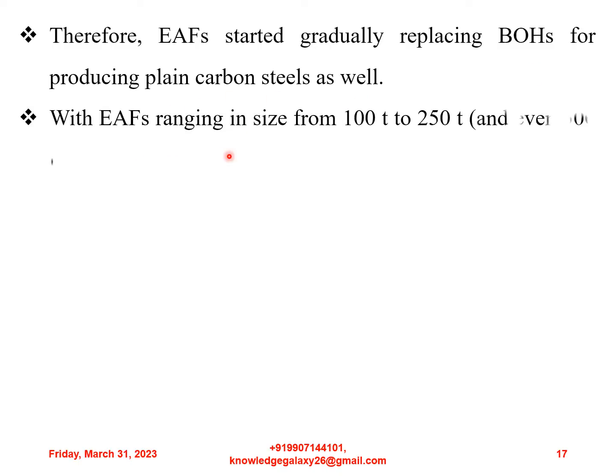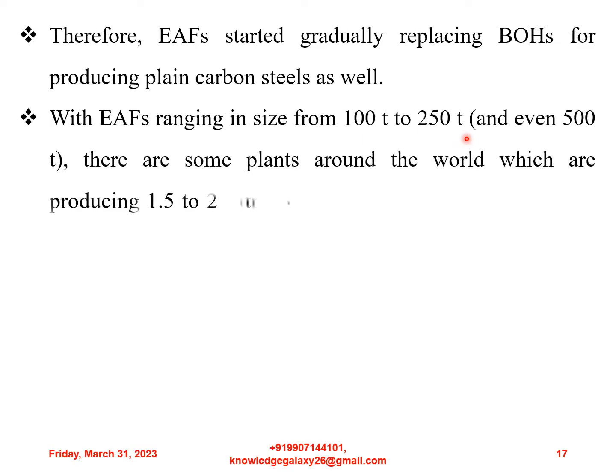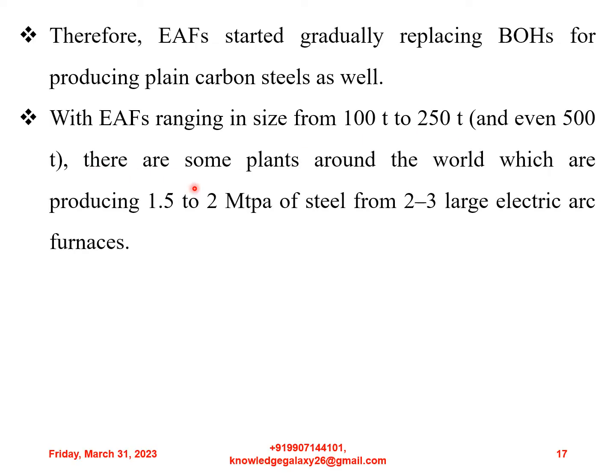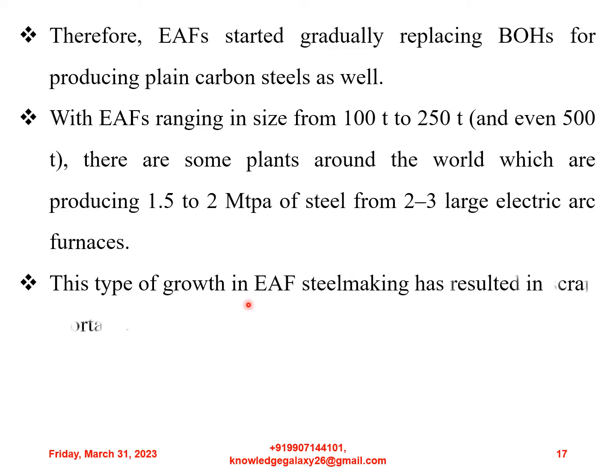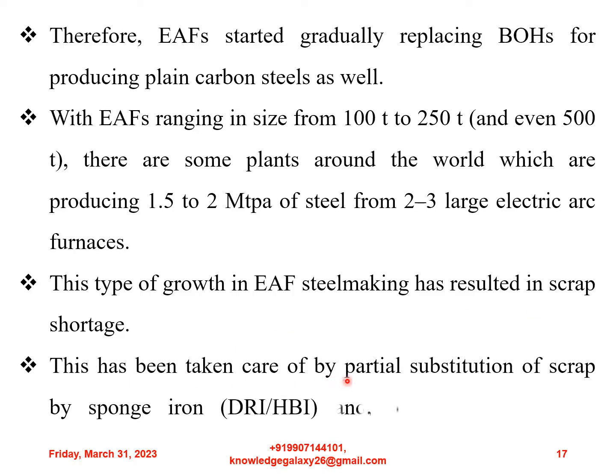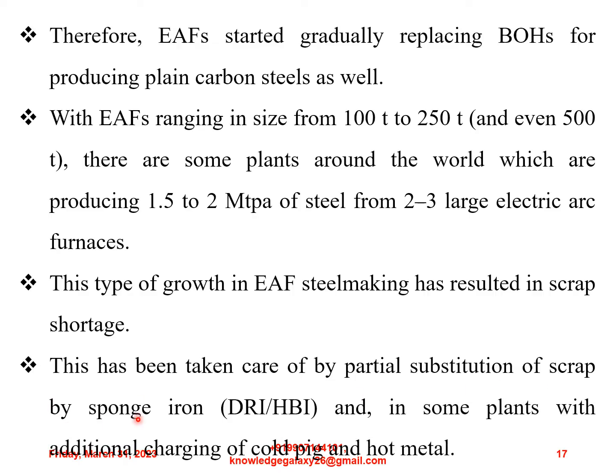With electric arc furnaces ranging in size from 100 ton to 250 ton and even 500 ton capacity, there are some plants around the world which are producing 1.5 to 2 million ton per annum of steel from 2 to 3 large electric arc furnaces. This type of growth in electric arc furnace steelmaking has resulted in scrap shortage. This has been taken care of by partial substitution of scrap by sponge iron, that is DRI or HBI. DRI is directly reduced iron and HBI is hot briquetted iron. And in some plants with additional charging of cold pig and hot metal.